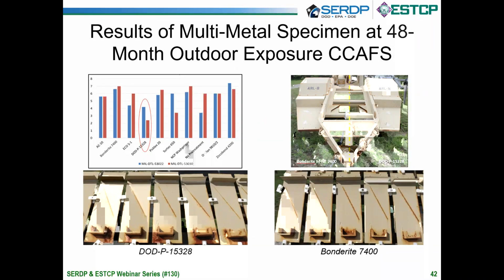And what you see in the bottom are some of the test samples that are out on the beach at Cape Canaveral, or were out on the beach at Cape Canaveral. Bonderite 7400, which was a Henkel product, is our leading candidate. It's a spray-in-place, dry-in-place type product, and it is certainly comparable to the wash primer in real world use.